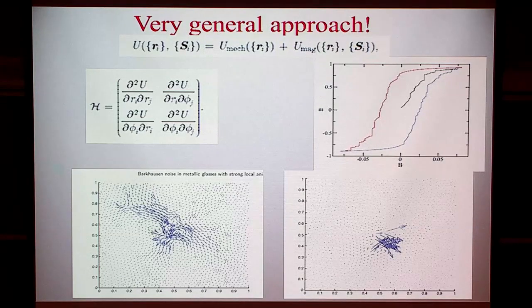Let me also make the point, coming back to Bob's statement yesterday, that in his cases it looks different. It does. In those cases you have friction, and therefore you don't have a Hessian matrix. Instabilities are still there, but you need to understand what the operator is. When you understand the operator, these eigenvalues and eigenfunctions are concentrated on the force chains, and the breaking of the force chains is the instability. So it's very different physics, but nevertheless you can use a similar approach if you know the right operator, which you need to find out.